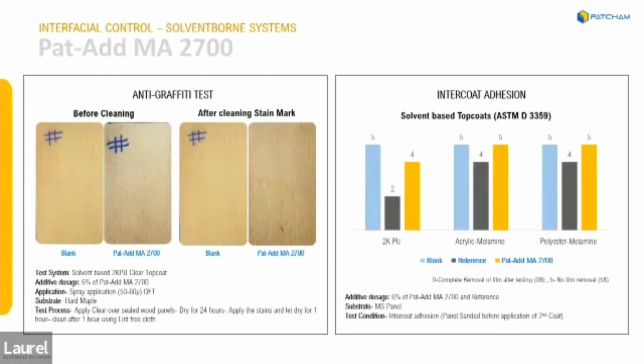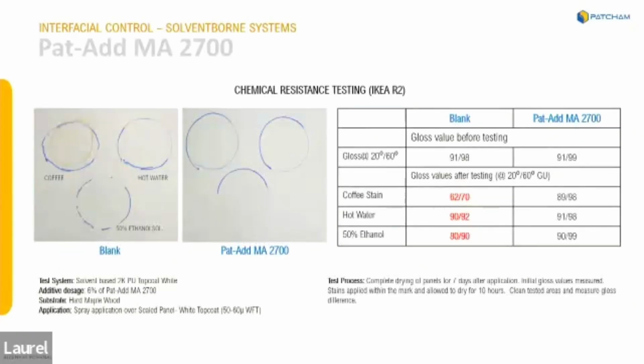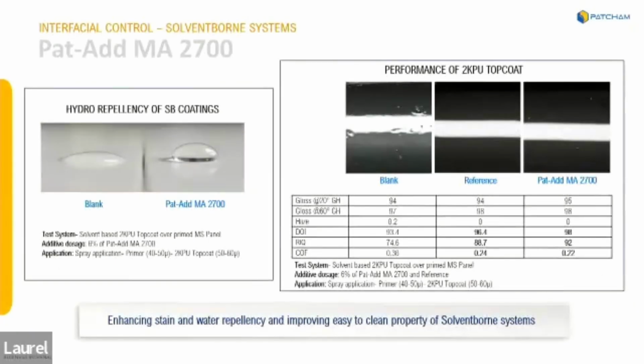So these are surface-modifying additives that have a hydroxyl functionality added to them so that they can participate with melamine cross-linking, two-component curing, and so forth, to provide then permanent surface properties that don't relocate themselves. And so you can see, compared to the reference and the blank, without the visual appearance that you get from these surface properties, because they migrate to the hydrophobic interface and then cure there when the film is cured and no longer migrate, captured by the polymeric structure.